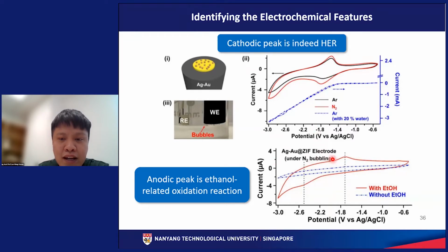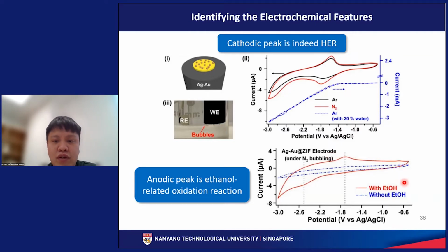So next, to affirm that the anodic peak over here is indeed indexed to ethanol oxidation, we also perform one control experiment, but in the absence of any ethanol spike into the electrolyte. So from the blue dotted line, we see the absence of the anodic oxidation peak, okay, and also the absence of a reduction HER peak. So this tells us that this peak over here is indeed due to ethanol oxidation. And the second point is that ethanol is important as a proton source for our NRR reaction.